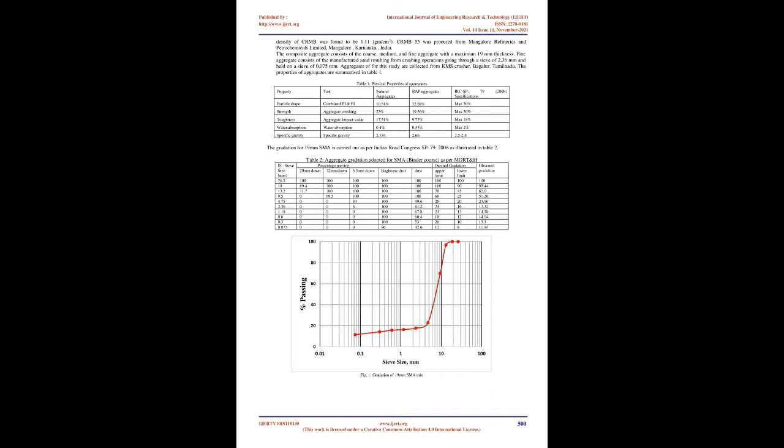An asphalt pavement, which is designed and constructed properly, will eventually undergo various types of failures due to various reasons such as number of years pavement served, type of paving materials used and due to other environmental factors etc. Tran et al., 2015, Ifran et al., 2018, and Wang et al., 2019. Among various types of pavement failures, rutting or grooving on the top layer is the major type of failure, reduces the life of the flexible pavements. This may be due to the insufficient compaction of base/sub-base layer or bituminous layers during construction. The type of mix used in pavement construction plays an important role for minimizing the rut depth.